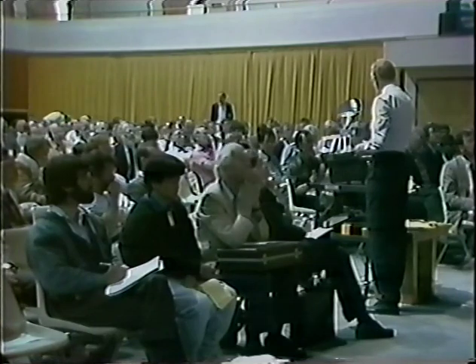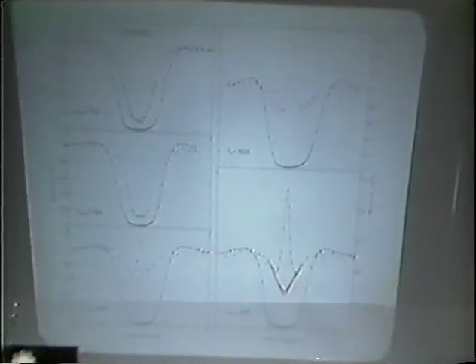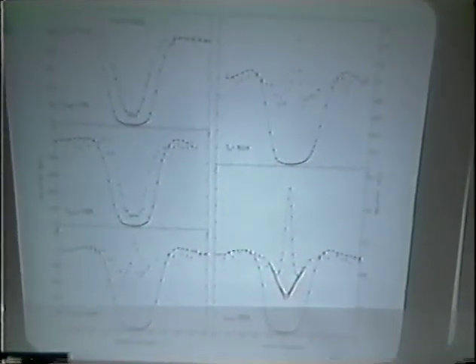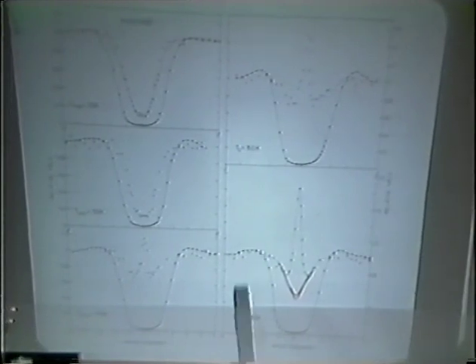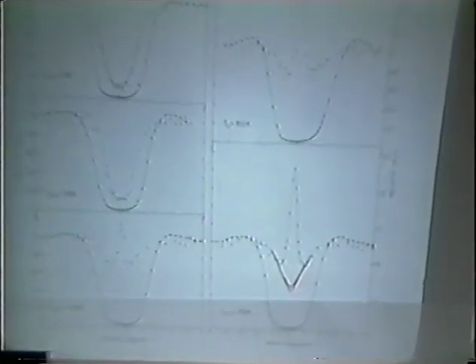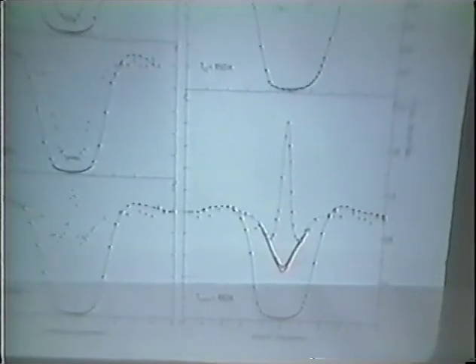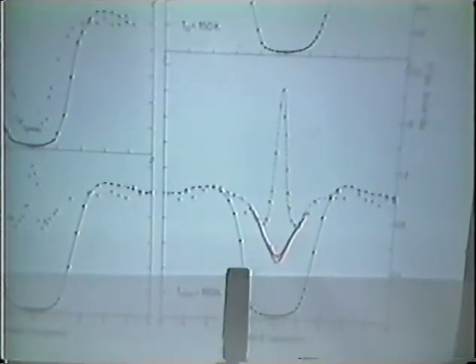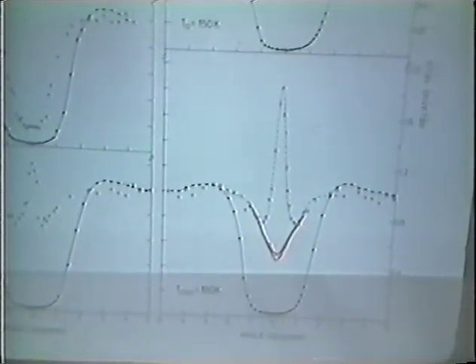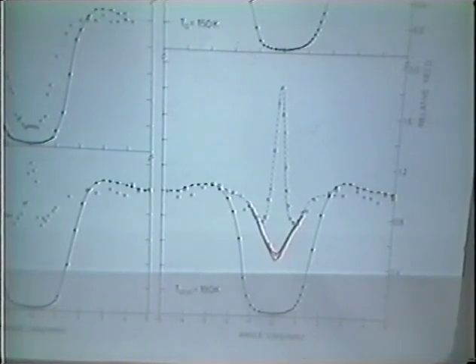I should now point out that if you try to put more hydrogen into the lattice, this delocalization behavior, this excited state, disappears. And if you, for example, come to a situation where you have 3 or 4 or even 6 hydrogen in a vacancy, they will sit very close to an octahedral site, which is also the case for the hydride, which has also been measured a long time ago with neutron diffraction studies.